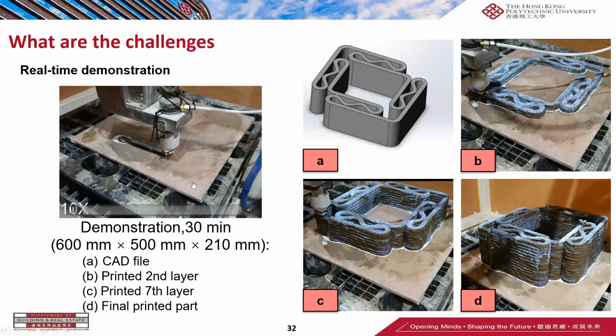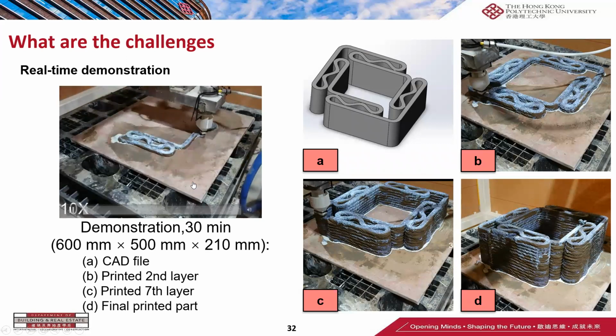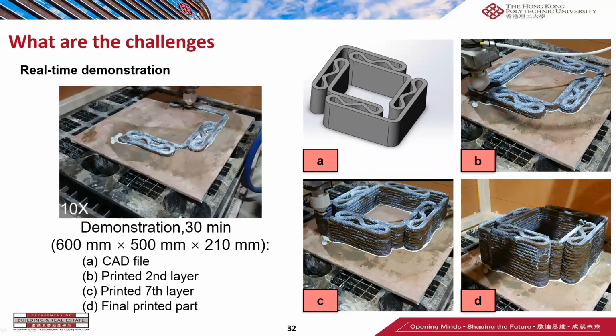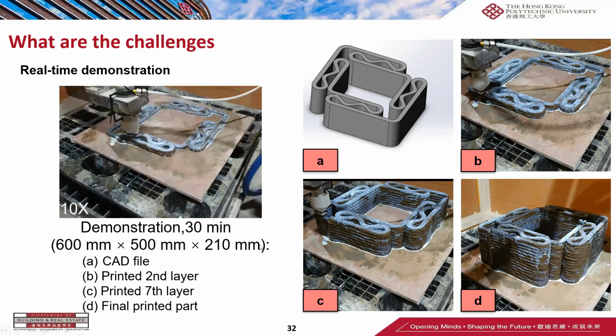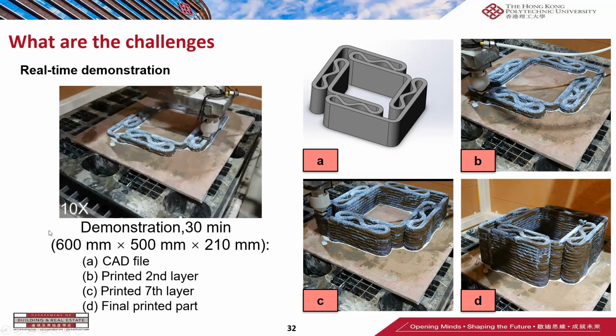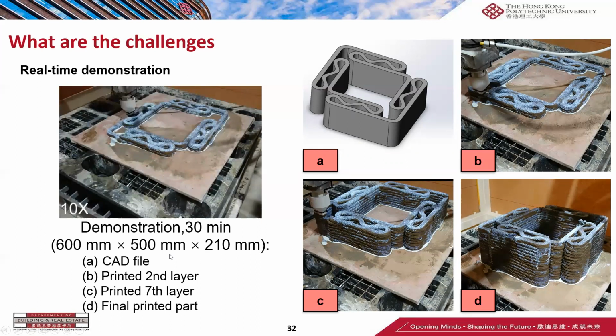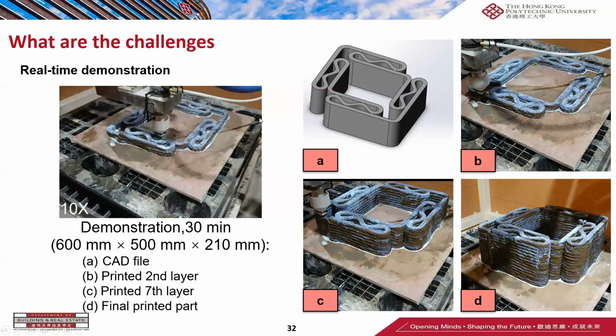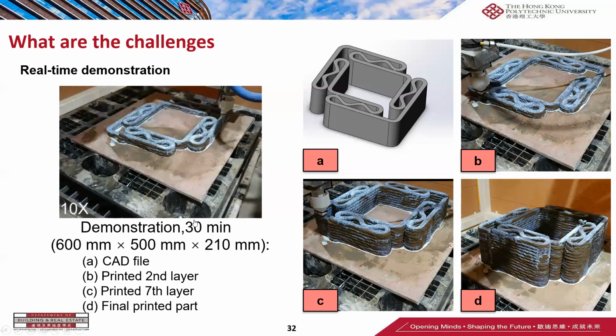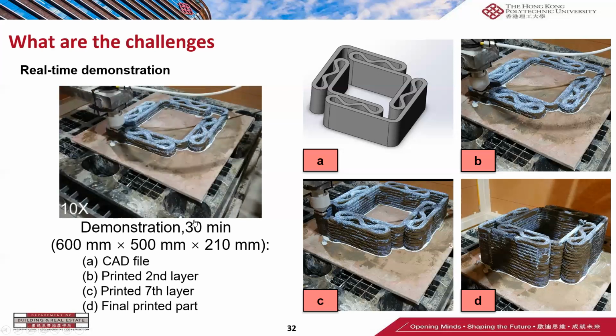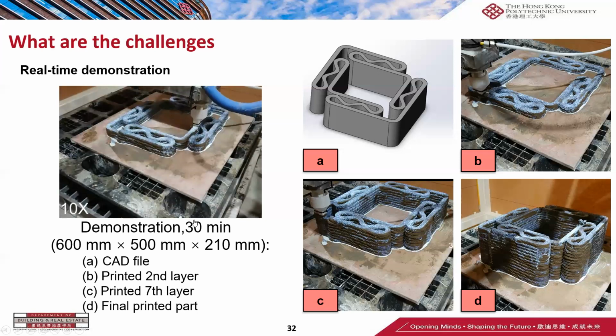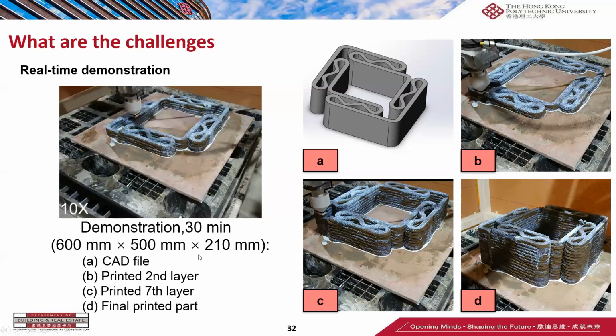Next, in order to validate whether all these methods can be used for practical applications, we have done a large scale printing test with this model, and this 3D model has this kind of dimension. The whole printing test took 30 minutes. So from this large scale printing test, we can understand that our nozzle has great potential to be used in practical applications to address the weak interface issue in the concrete printing process.